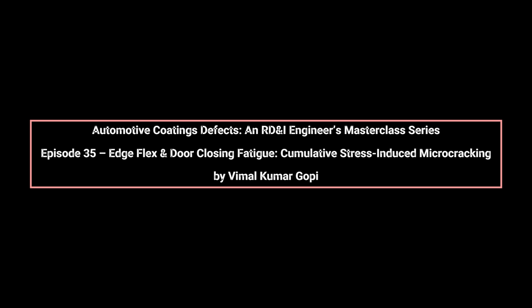Primers are critical fatigue buffers. Flexible primers absorb and distribute strain before it reaches the decorative layers. Without sufficient primer compliance, fatigue stress is transferred directly to the base coat and clear coat, accelerating microcrack initiation. This is why edge fatigue failures often appear as clear coat cracking first, followed by adhesion loss and corrosion progression.